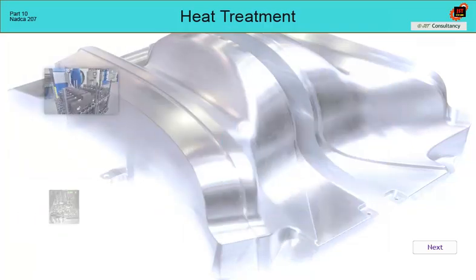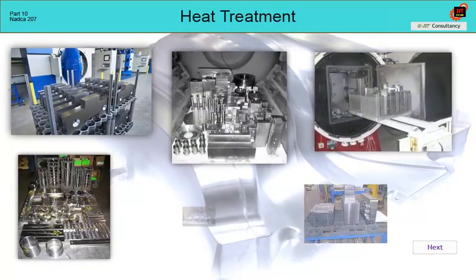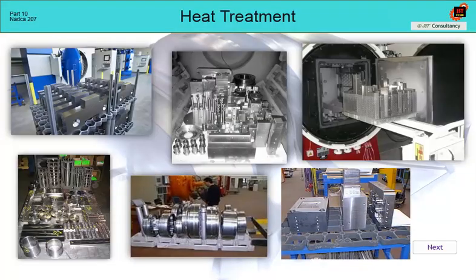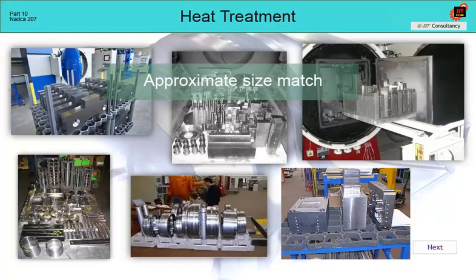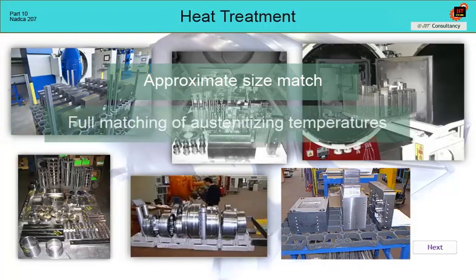In vacuum heat treatment, it is common practice to create mix batches. Their appearance is diverse and cannot usually be predicted precisely because it involves the processing of completely individual pieces. In order for the heat treatment of these batches to take place according to the usual parameters, 2 basic criteria must be observed: approximate matching of dimensions and full matching of austenitizing temperature.